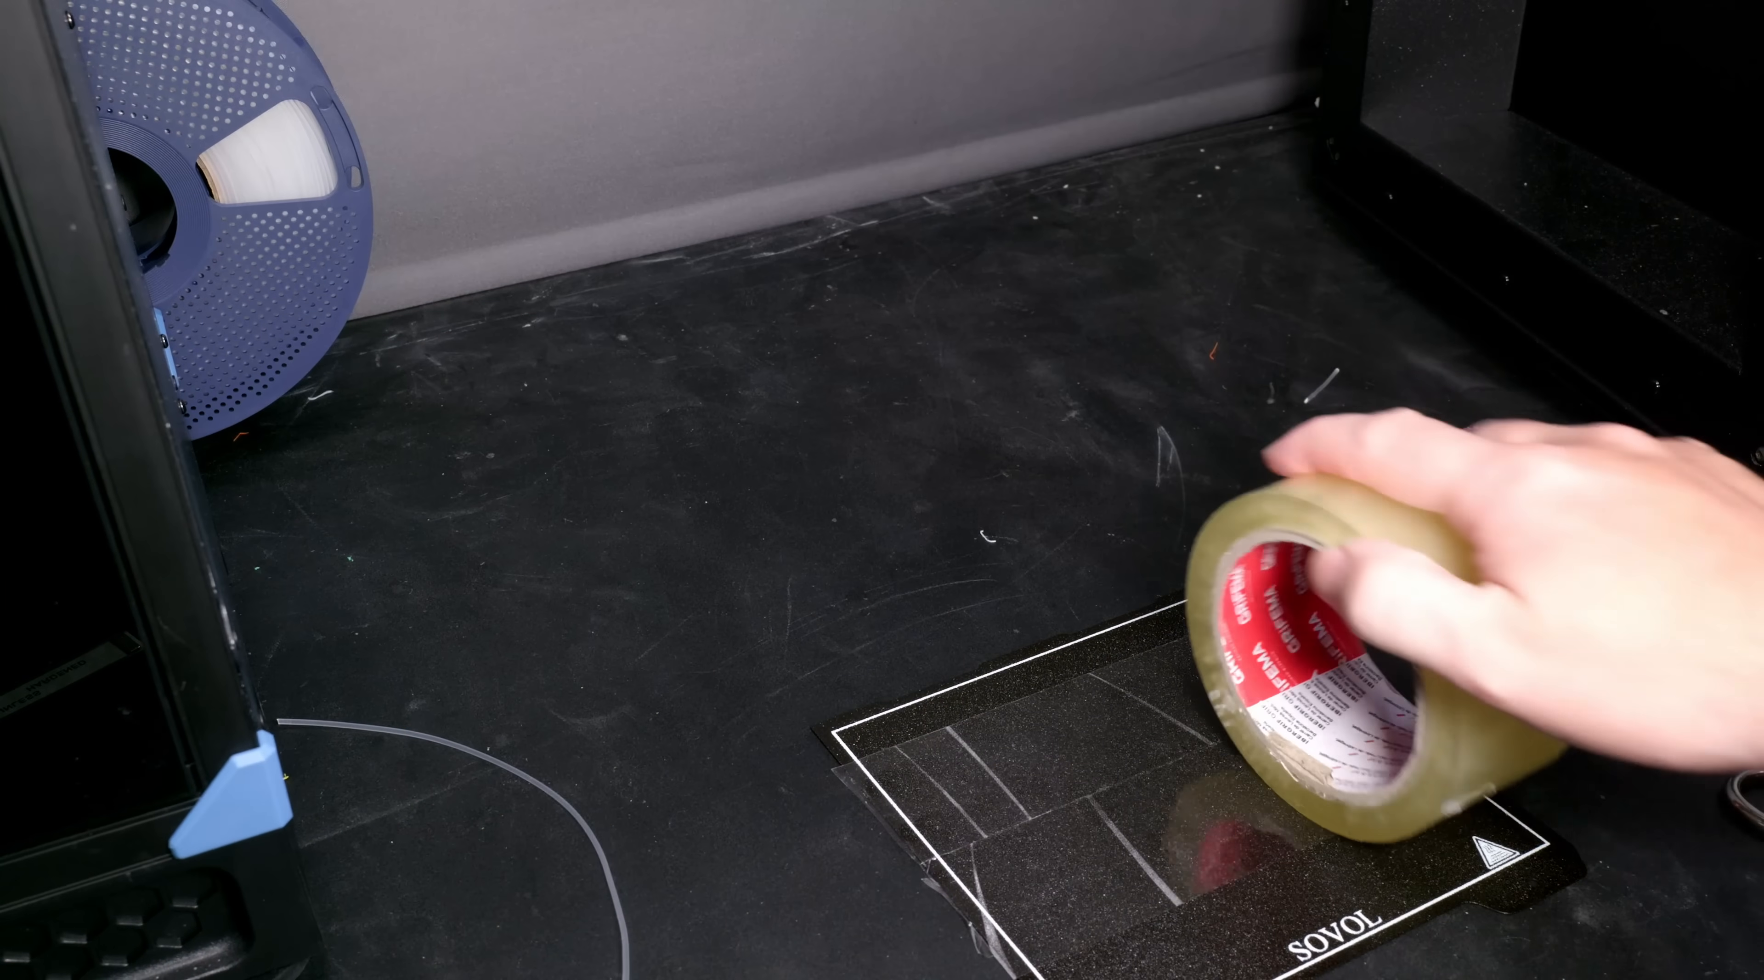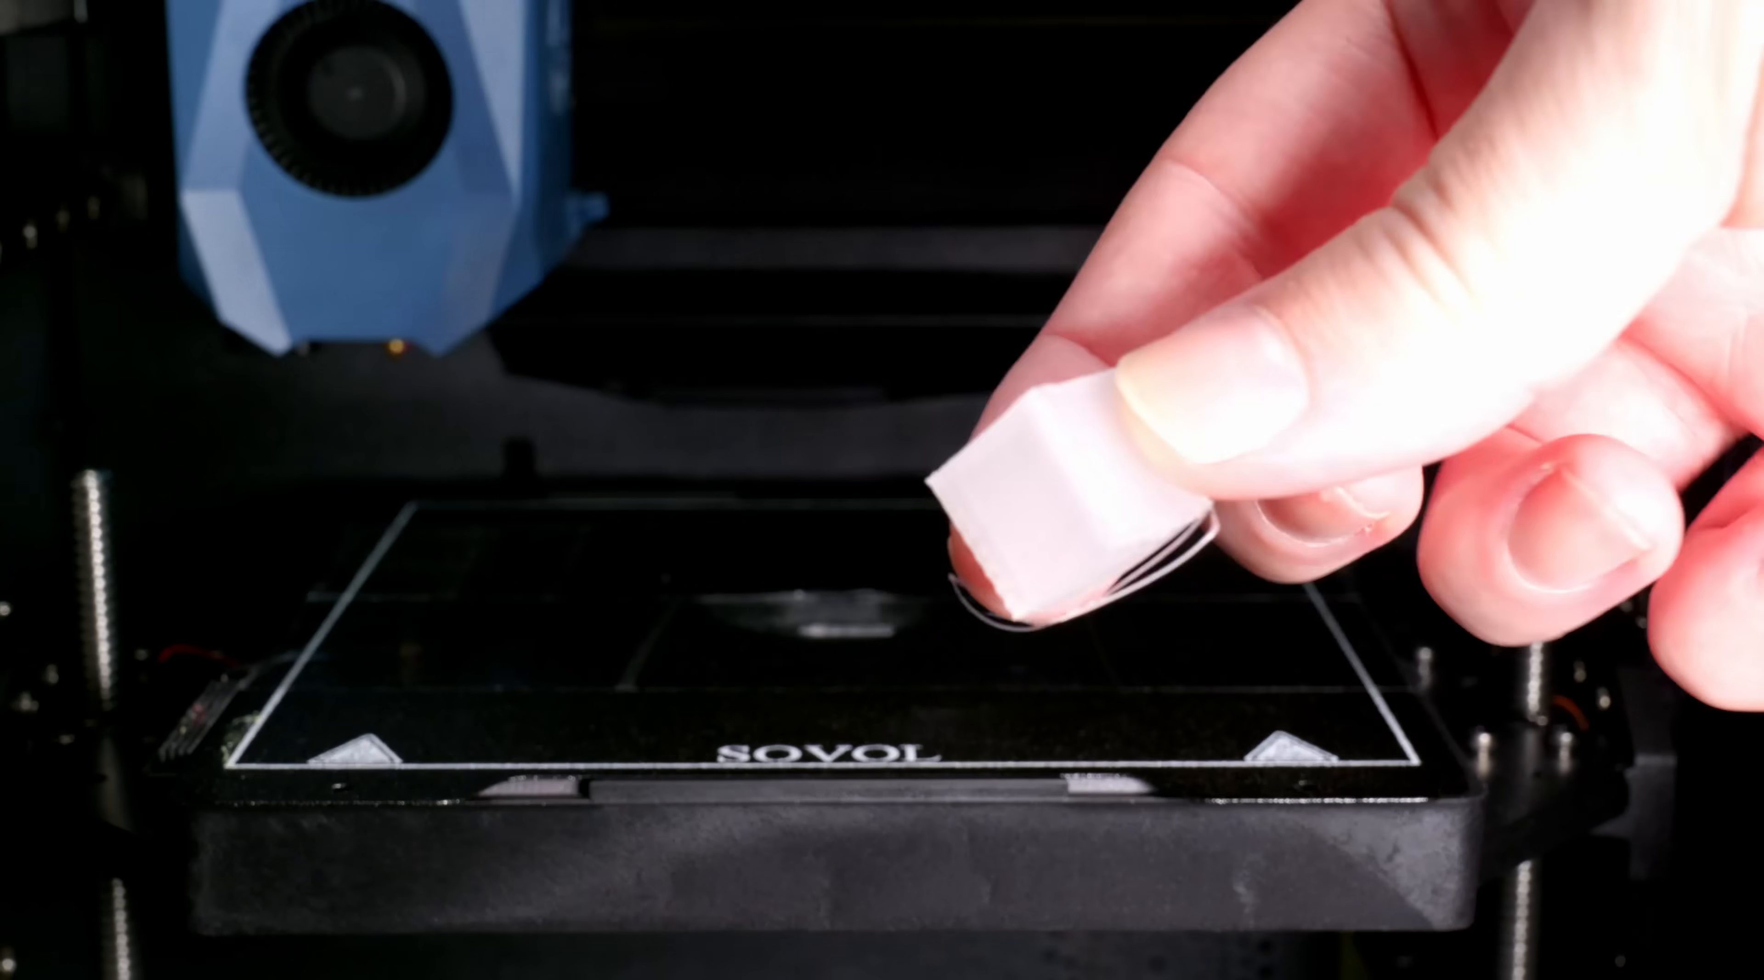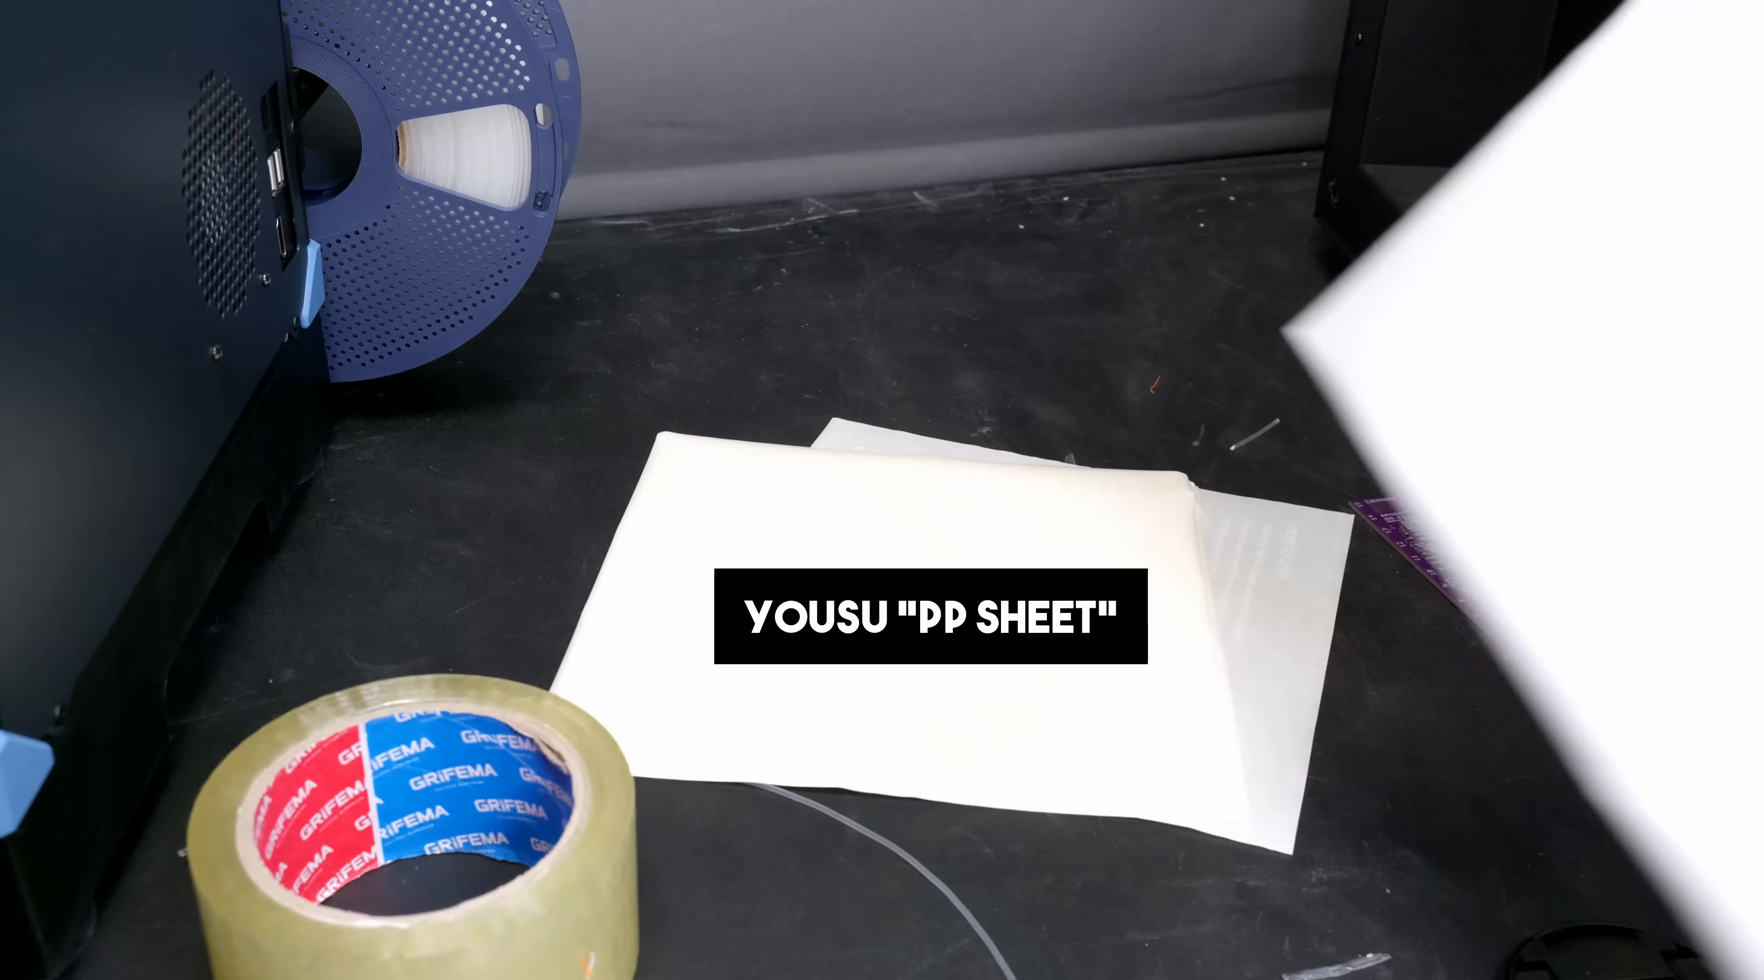But luckily normal clear wide sticky tape, usually but not always nowadays because you've got these eco-friendly ones coming into the market, but usually if you buy the cheap stuff it's made of polypropylene so that's what people have been using since forever as a print bed. If you go for decent quality stuff, I know I just told you to go for cheap stuff but if you go for stuff that sticks well and I recommend that you obviously check it's polypropylene so the one I'm waving around in front of the camera it is really sticky and I had zero problems sticking it to the Sovol bed here. I didn't think it would stick this well because traditionally you would stick it to glass and it prints fine, so problem solved. I'm actually not kidding, this is the easiest, simplest, most foolproof way to print polypropylene in my opinion.